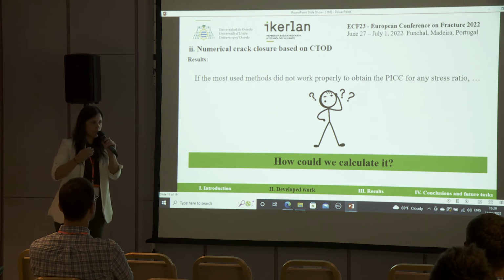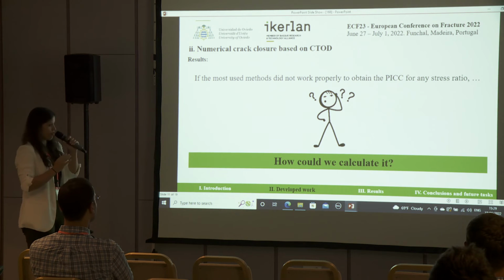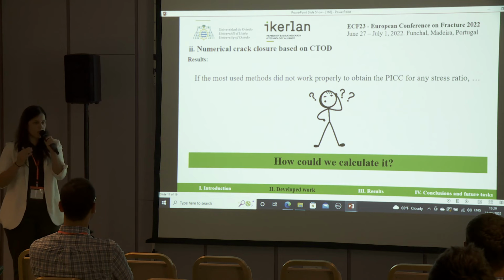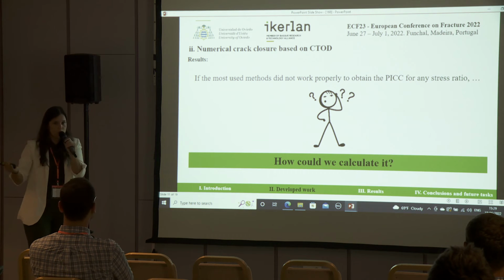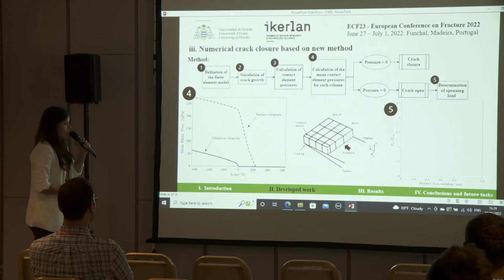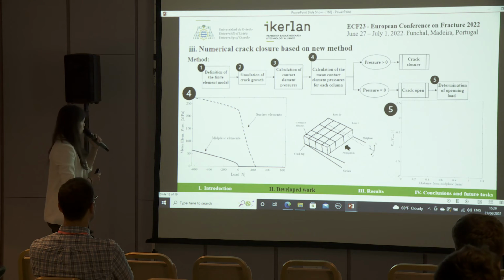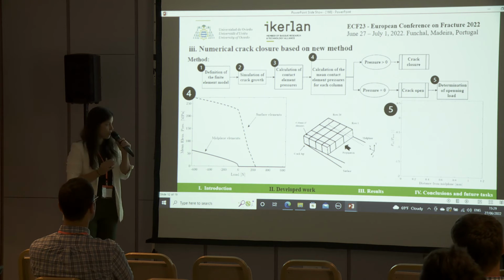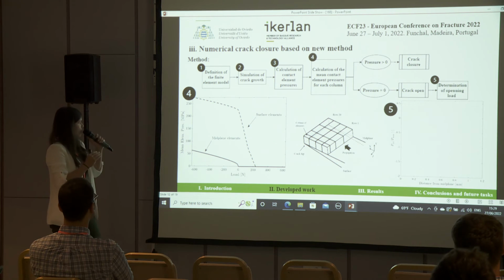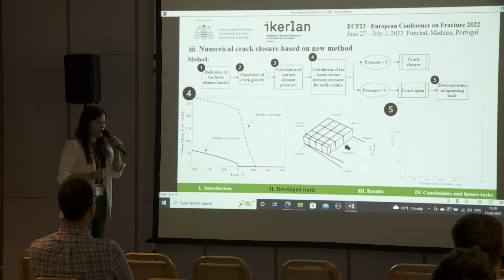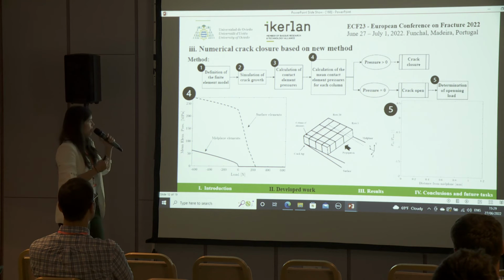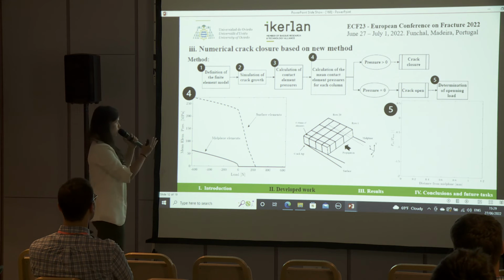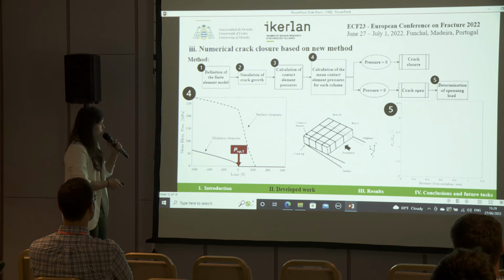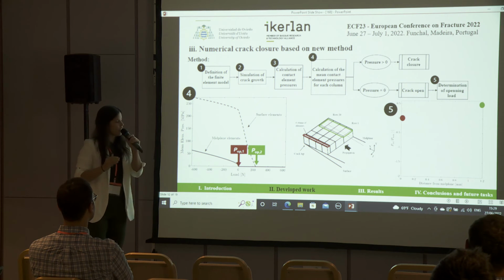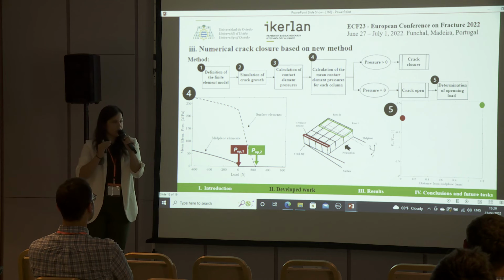So at this point, the following problem appeared. If the most used method did not work properly to obtain the crack closure distribution under negative stress ratios, how could we calculate it? Well, to solve this problem, we propose a new method based on 5 steps. The first step was the definition of the finite element model, then the simulation of the crack growth. In the third step, the calculation of the contact element pressures. In the fourth step, the calculation of the average of contact element pressures for each column. And finally, in the fifth step, the determination of the opening load.